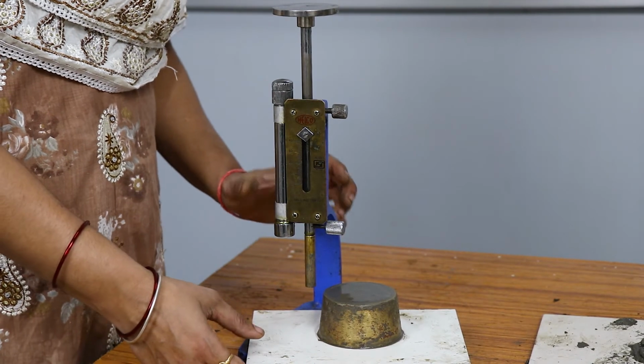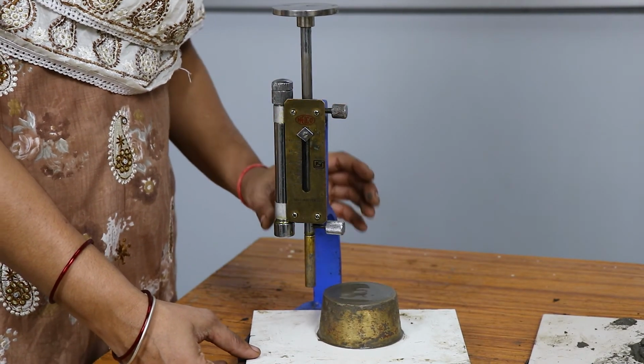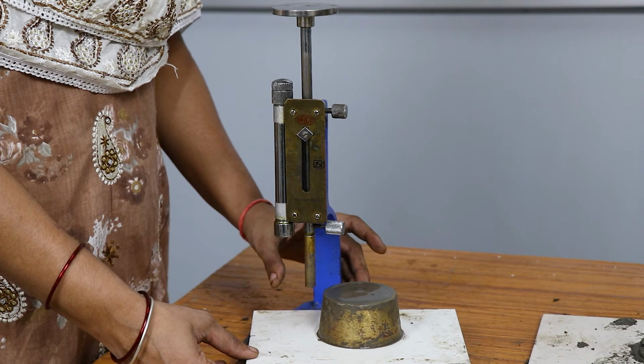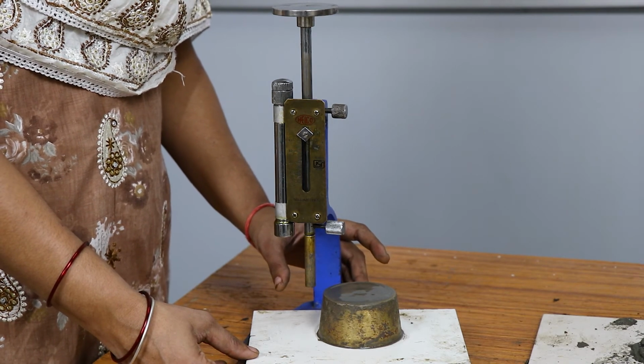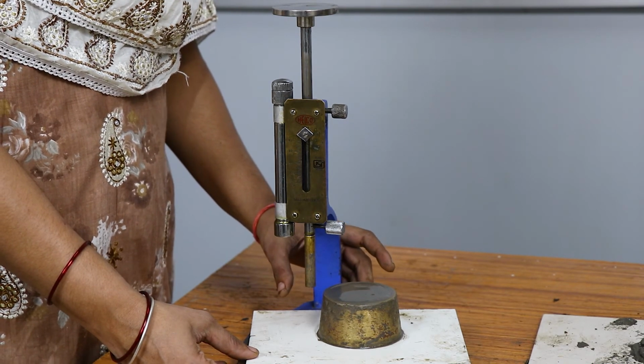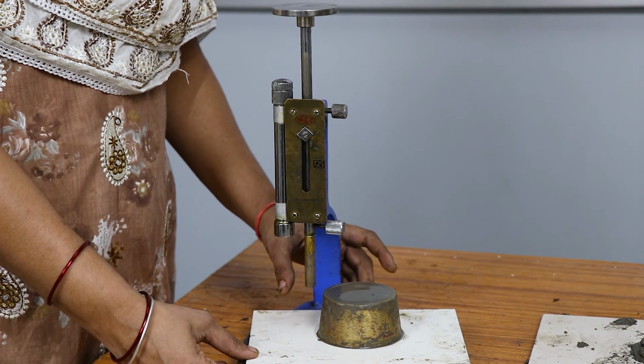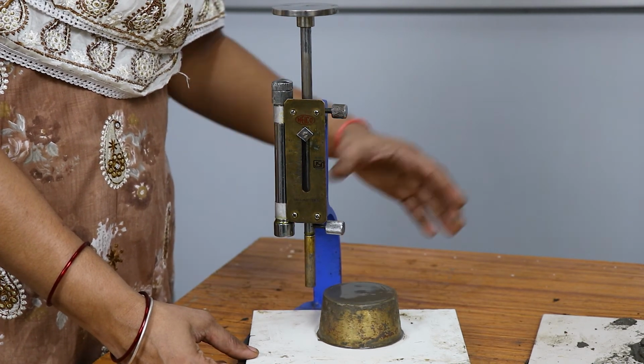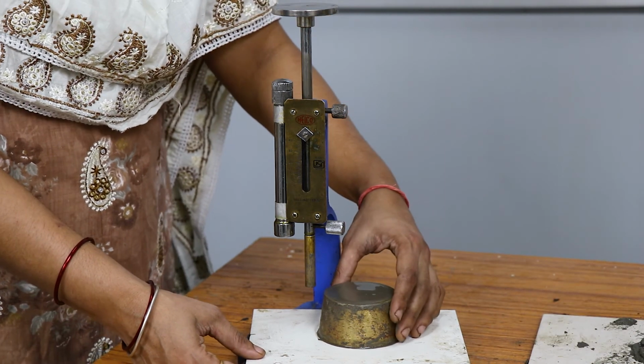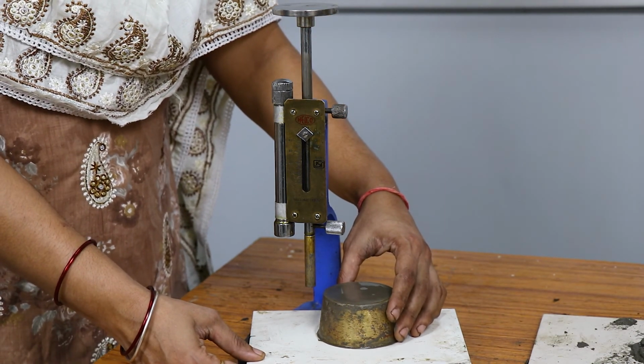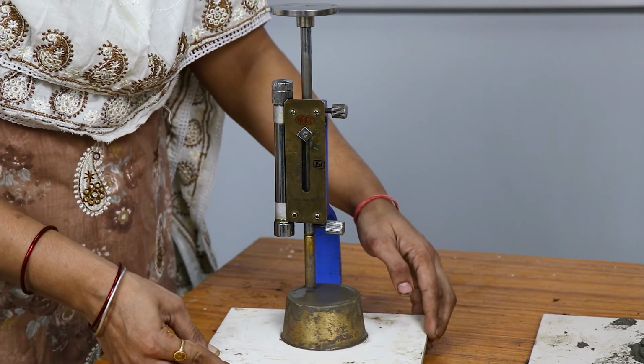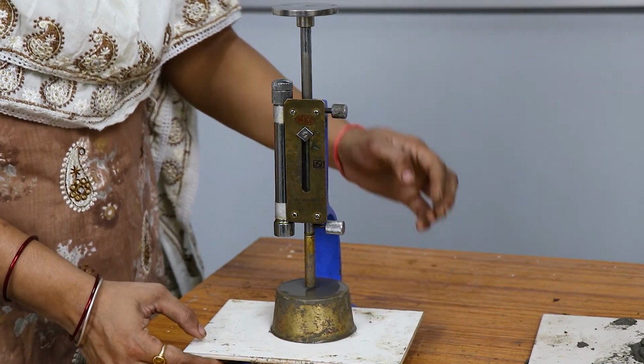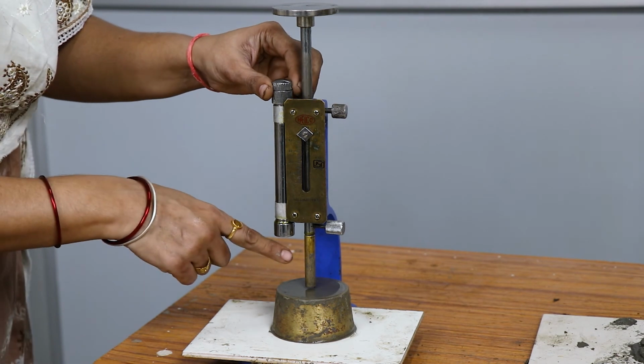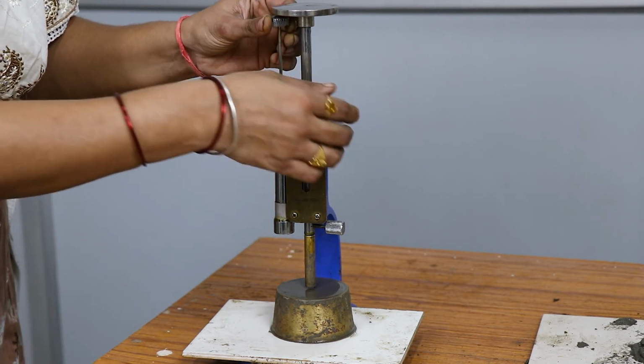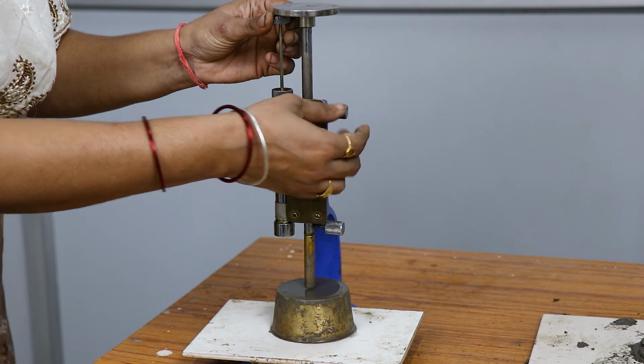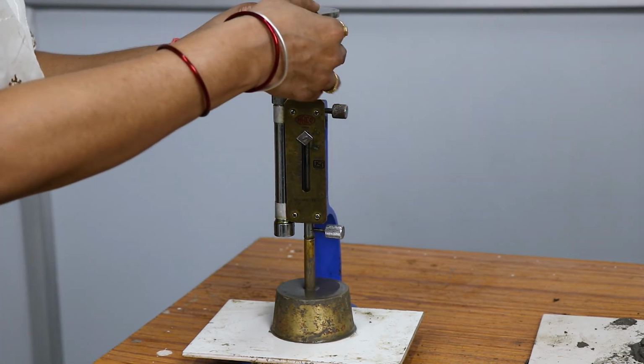Further, we have again taken 400 grams of sample, and now we have added 31% of the weight of the dry cement sample, so it comes out to about 124 grams of water. We have weighed it and we have prepared the cement paste. We have filled that cement paste in the Vicat mold, and again we will carry out the test for the penetration. We will measure how much is the penetration corresponding to 31% of water.